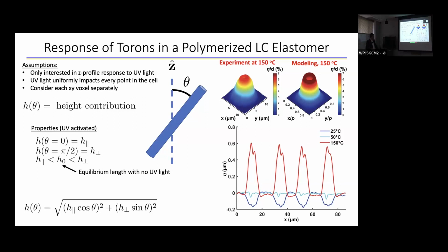And so now, as we numerically minimize the free energy of the liquid crystal, we can get energy minimizing director field configuration that we have before polymerizing it. Then we cross-link, we freeze it, and then we change temperature and it actuates. So we have the director structure from minimization, and then we can apply this response in here, in terms of expansion coefficient. And then, with that, we can model the actuation of the height of the sample. So indeed, we can reproduce the behavior.